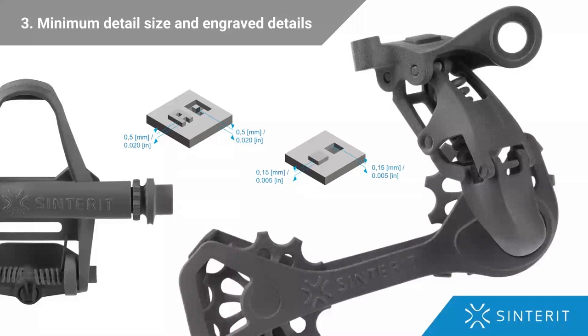To put it simply, you don't need to restrain yourself nearly as much, and it's important to make use of that. So you also need to be aware if you want to put some embosses or engraved details, letters or digits, and so on. If so, the minimal thickness for embossed details should be around 0.15 millimeters of height. And for engravings, it should be 0.15 millimeters in depth. For letters or digits, it should be 0.5 to 0.6 millimeters of extra height if you want to receive an emboss, and 0.5 millimeters of depth when dealing with engravings.